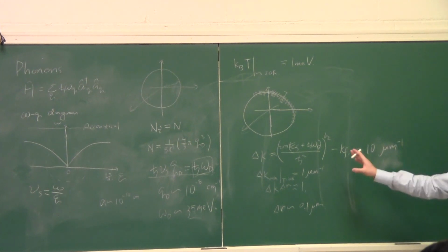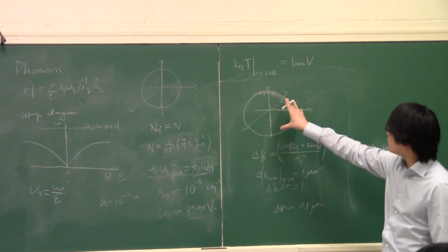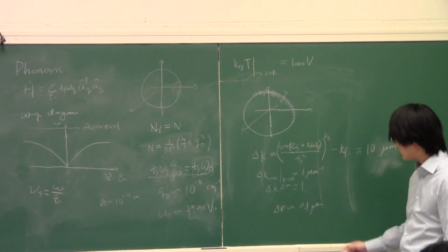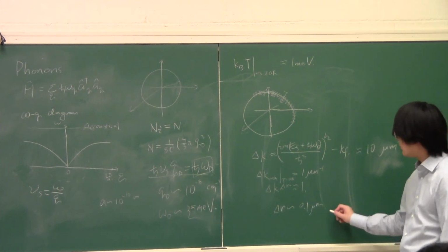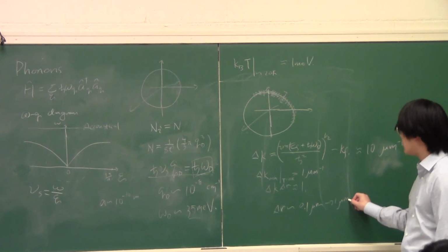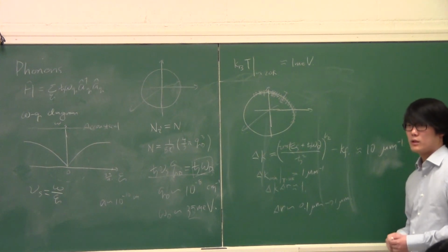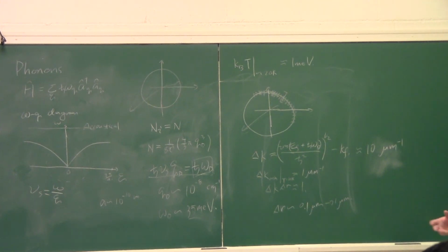So we know that if I were to sum up a wave packet over here, then the spread of the wave packet goes from 0.1 micron to about 1 micron. Okay. And what is the significance of this value? Well, it turns out that later when we try to assemble these two electron wave packets, we can think about them as being one particle with the reduced mass, having roughly the same spread of wave function. It tells you that roughly these two electrons are going to be separated by this much.